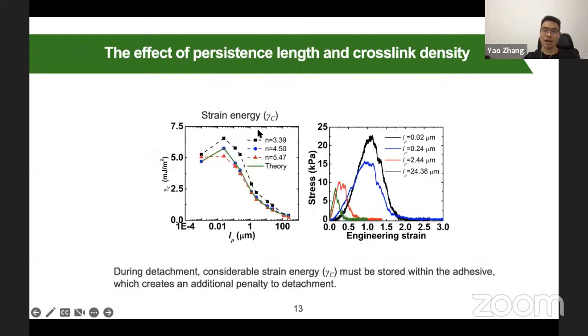The second, you have to do some extra work. This work is stored in the network, which is the strain energy. So if you have a softer network, it's easier for the network to store strain energy, which in turn will give you a larger work of adhesion.